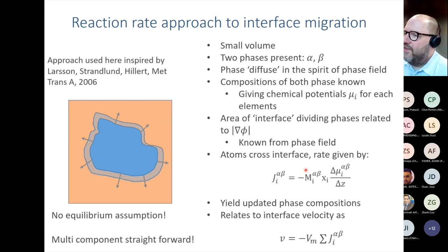And we can relate that to an equation similar to this one, which has been derived using the absolute reaction rate theory and using that in order to describe the migration of an interface. And that was actually the achievement of that paper I mentioned earlier. From that, we actually get new phase compositions because we know how many atoms will cross the interface, and we get an interface velocity. So we get a way to calculate by how much the interface would have moved and how much of one phase has transformed into the other. Just the challenge now is how to couple that into phase field.